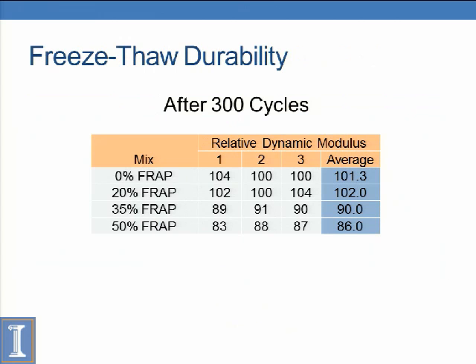We also did freeze-thaw durability. So with this, you have prisms again, and you subject it to freezing and thawing cycles underwater. You have a prism in this chamber that goes down to 0 degrees Celsius and then goes up to 40 degrees Celsius and just alternates between those cycles, and we measure it intermittently every 36 cycles or so. So the test is ended at 300 cycles, and our relative dynamic modulus you measure was pretty good. All the mixes, the lowest was the 50% FRAP at 86%.